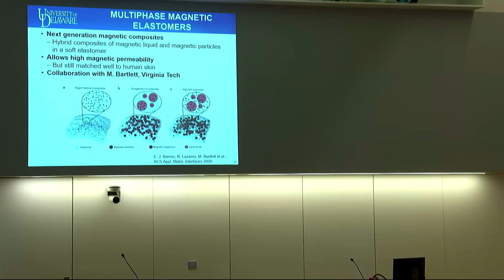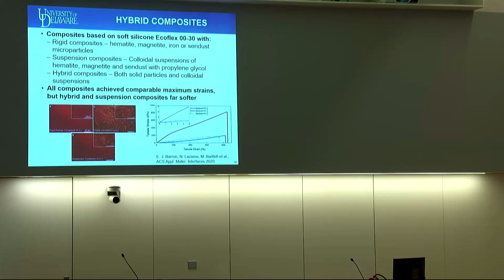So working with a collaborator, Mike Bartlett, down at Virginia Tech, we looked at using more of a hybrid composite approach, combining magnetic liquid with magnetic particles in a soft elastomer. Looking at a few different options, the rigid particle composite would be similar to the ferroelastomer that I just talked about. The suspension composite has colloidal suspensions, and then the hybrid combines both effects. So we're trying to maintain our low mechanical stiffness, but still have a higher magnetic permeability. In this case, we have our rigid composite looking at a variety of different particles: hematite, magnetite, iron, and sendust. The suspension composite has suspensions of these particles in propylene glycol. And finally the hybrid combines both.